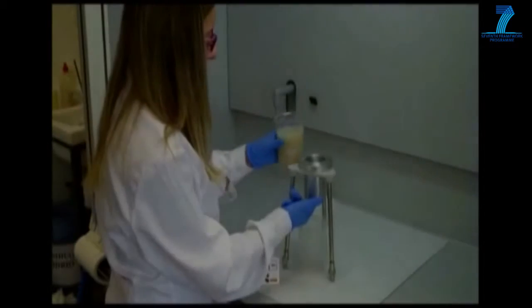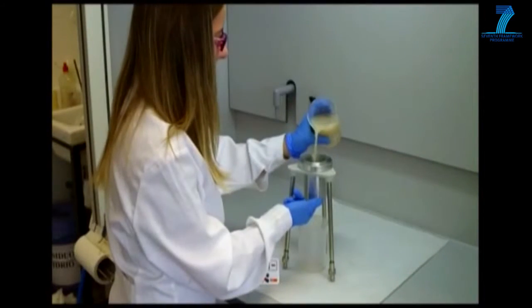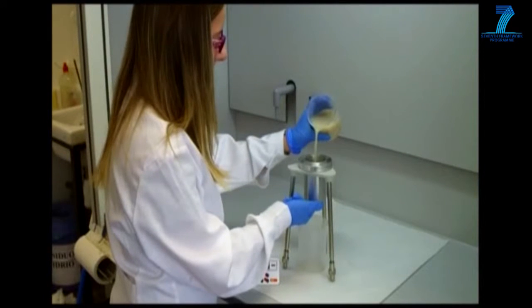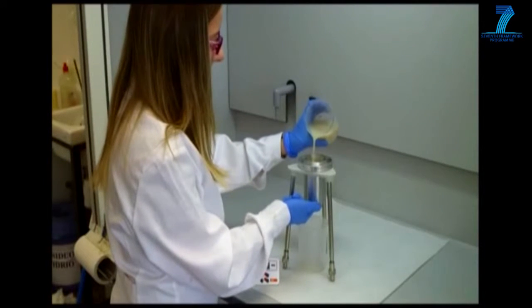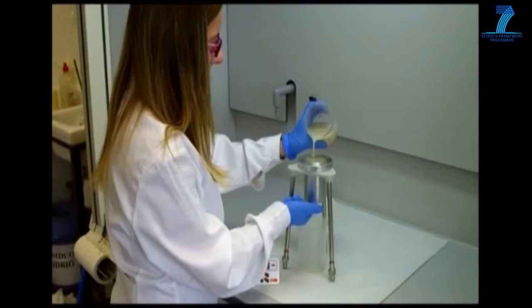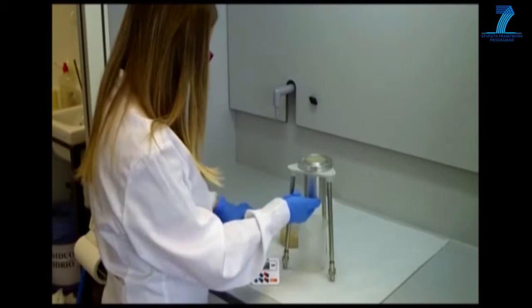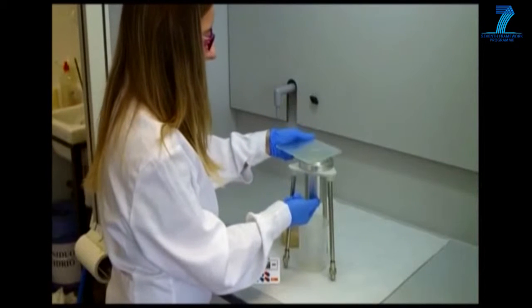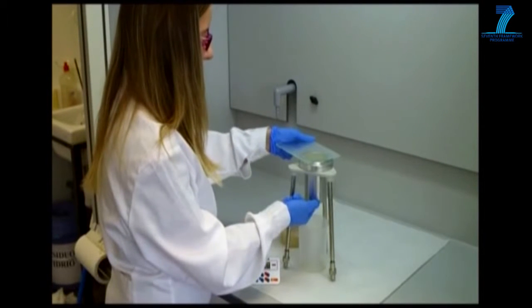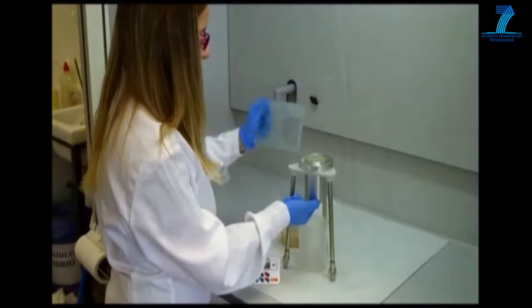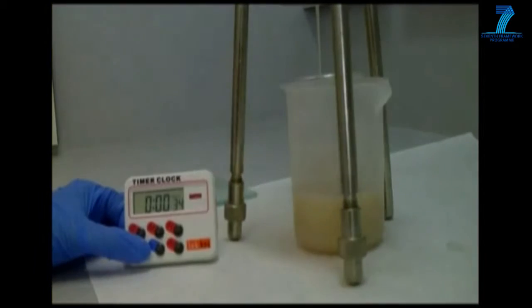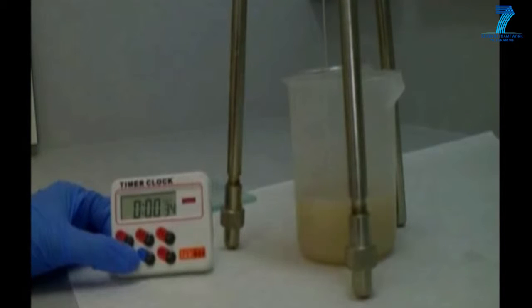Viscosity is measured by viscometers, but in practice it is assessed from the flow time measured by the EN ISO standard method. We have to choose the appropriate and calibrated flow cup so that the flow time will be between 30 and 100 seconds. The industry is very often still using DIN flow cups, for which the standard was withdrawn. We must be aware that flow time measured by the DIN cup is totally different compared to the one measured by the ISO cup with the same orifice.